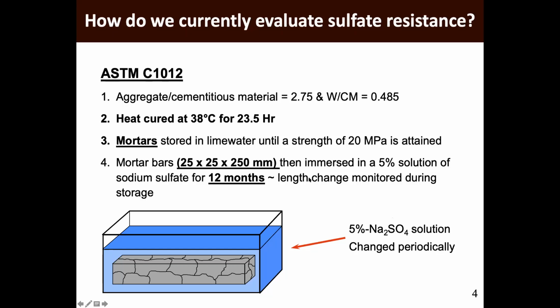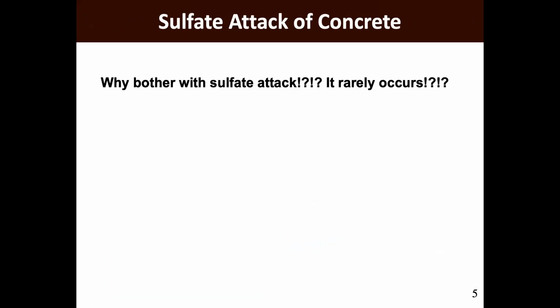But the drawback of this test method is that it takes about 12 months to collect any real data. Usually we refer to ACI 201, which is the durability specification, to determine whether we have good resistance or not. It's based on a 6, 12, or in some cases even 18-month data point that we have to get. So it's really an issue in terms of the length of time to get significant data.